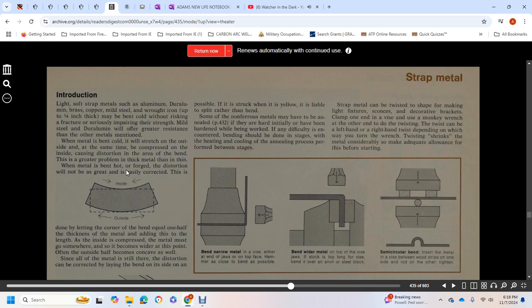When metal is bent cold, it will stretch on the outside and at the same time compress on the inside, causing distortion in the area of the bend. This is a greater problem when the metal is thick than when it's thin. When metal is bent hot, or forged, the distortion is not as great and is easily corrected. This is done by letting the corner of the bend equal 1/2 the thickness of the metal, adding this to the length. On the inside the compressed metal has to go somewhere, so it becomes wider at the point, and often the outside of the bend becomes concave as well.